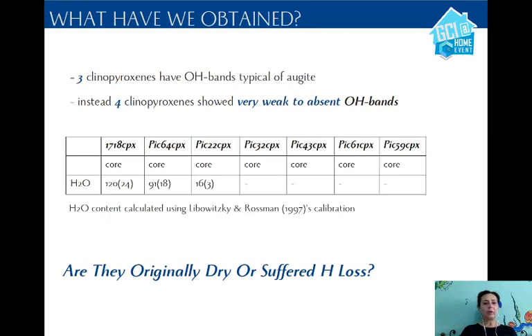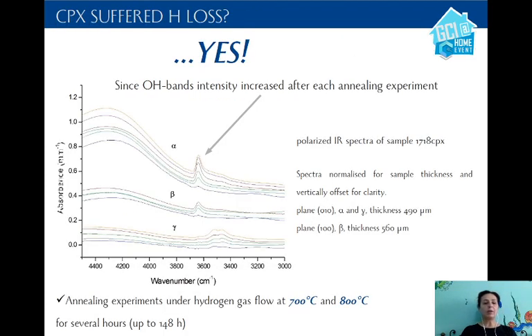So coming to the results, we observed in the infrared spectra OH bands, typical of augite composition, only on 3 samples. The remaining 4 have very weak to absent OH bands, and if we estimate the water content of these clinopyroxenes, we go from 0 to 120 ppm. This great variability in the OH content of our samples posed us a question: if these samples were originally dry or suffered hydrogen loss. To answer this, we